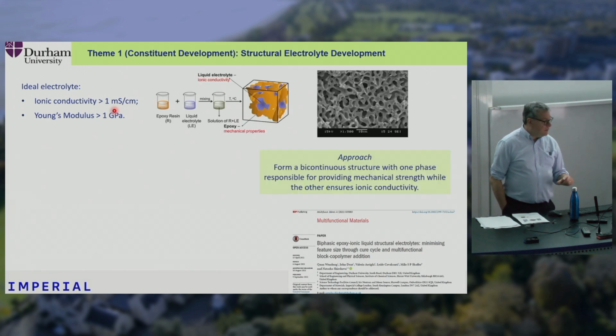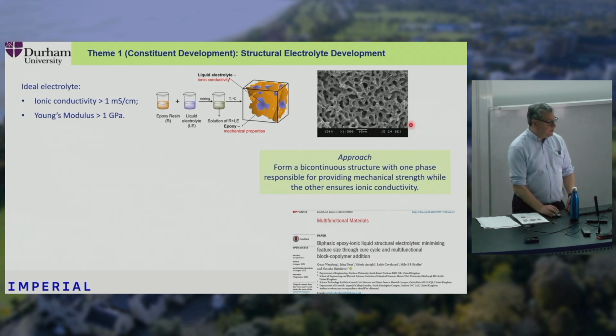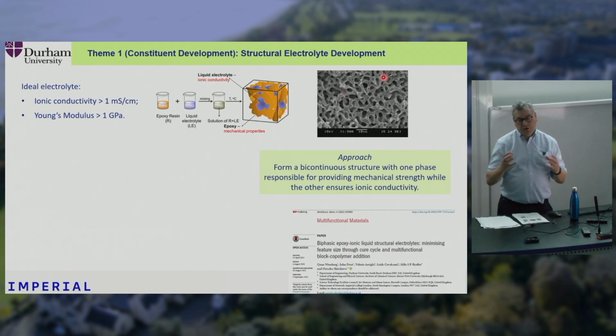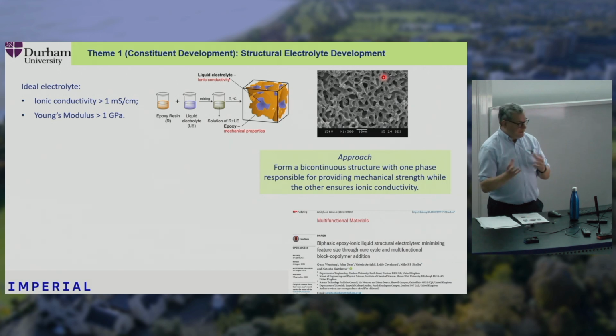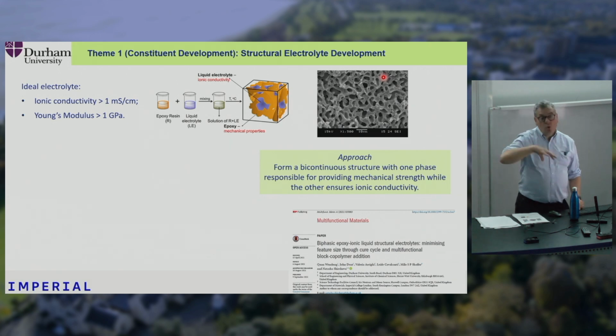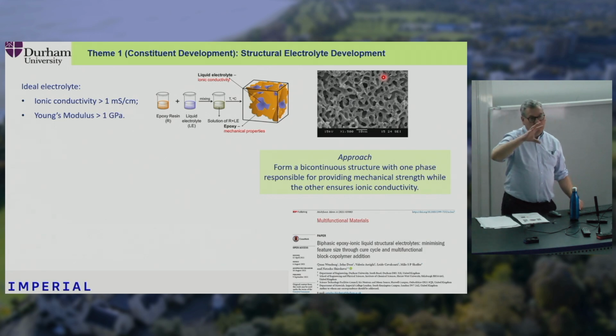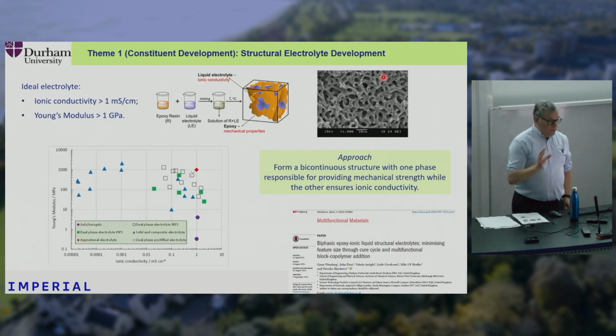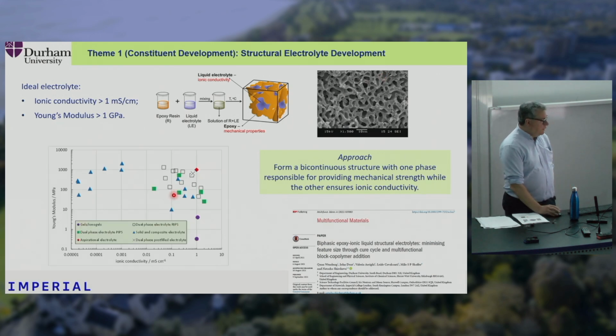The approach we've taken has been to mix epoxy resin with an ionic liquid and to produce this biphasic structure. So this is showing you the microstructure of that material. We've washed out the electrolyte and it's just left the sort of porous structure of the epoxy. And what we've been doing has been modifying the proportion of the ionic phase and the structural phase to modify that microstructure.